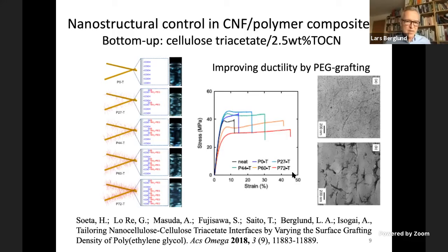So what he did was that he started with TEMPO fibrils. So if you see in the left-hand side here, we have electronegative carboxyl groups. And then he added polyethylene glycol, which has electropositive charge at the end. And then he can control the density of his grafts. And by controlling the density, he can then control ductility of his nanocomposites. He has something like 2.5% cellulose and then he can control the ductility.